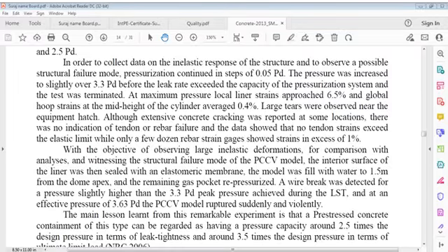At maximum pressure, local liner strains approached 6.5% and global hoop strains at mid-height of the cylinder averaged 0.4%. Large tears were observed near the equipment hatch. Extensive concrete cracking was reported at some locations. There was no indication of tendon or rebar failure, and data showed that no tendon strains exceeded the elastic limit, while only a few dozen rebar strain gauges showed strains in excess of 1%.